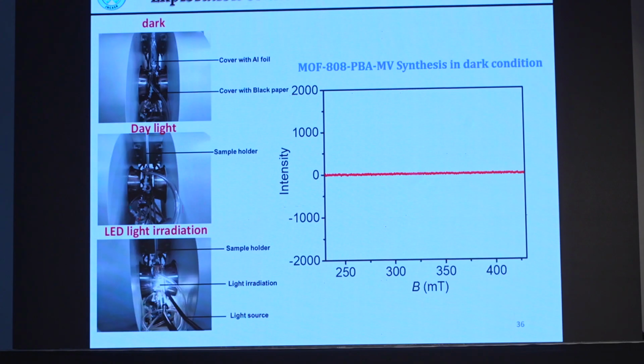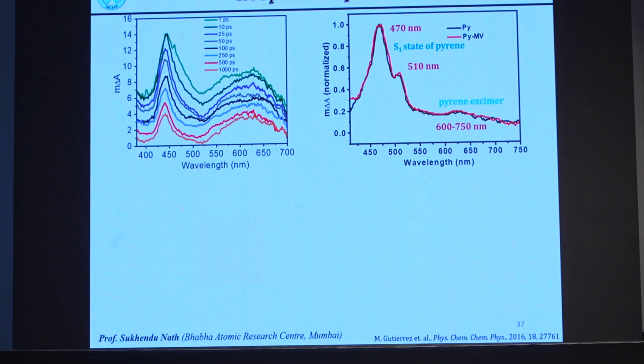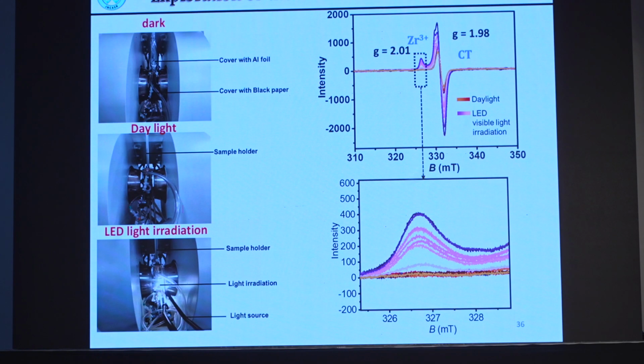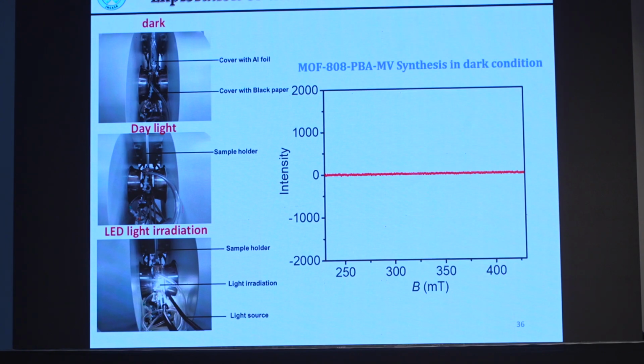Then we try to understand it with EPR. This is light induced, so you can do in situ EPR, okay? Now with the methyl viologen, zirconium is 4 plus, there is no d electron, but electron transfer is happening and you are getting zirconium 3 plus, g equals 2.01, as well as the CT also increases. That is showing that indeed electron transfer is happening, okay?